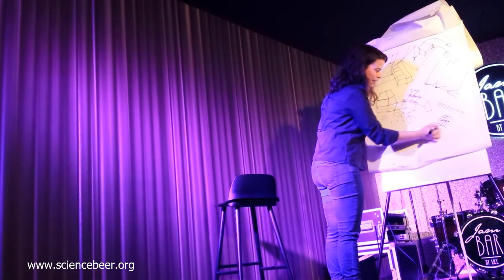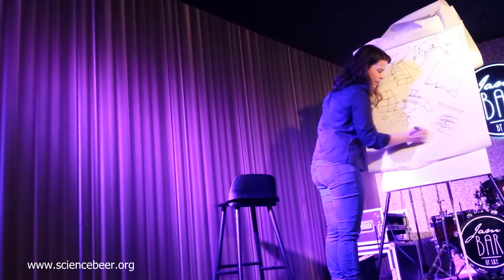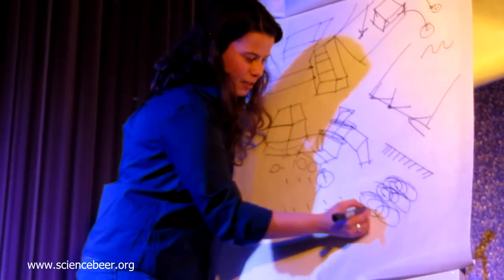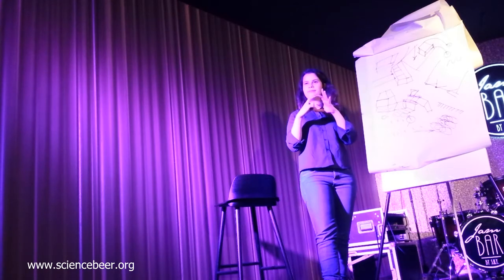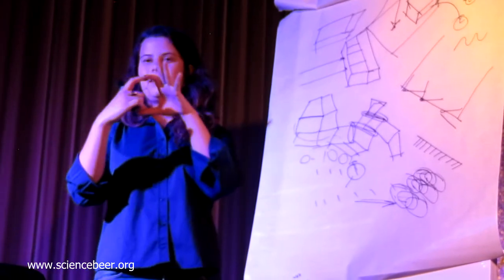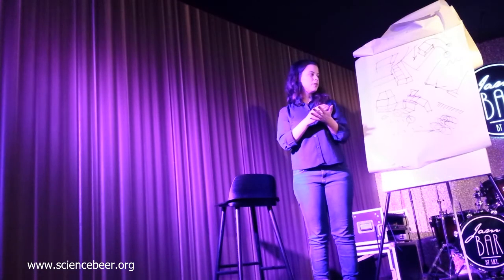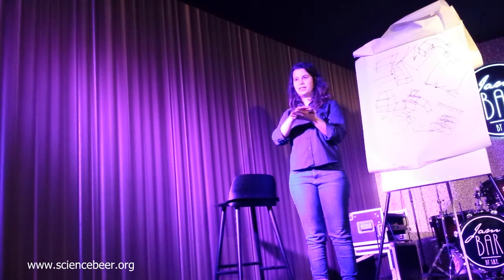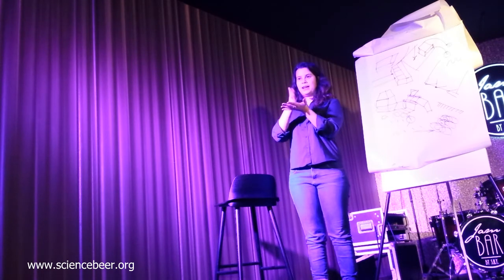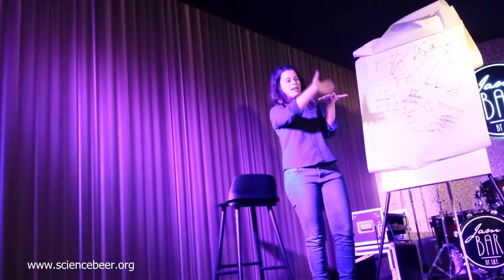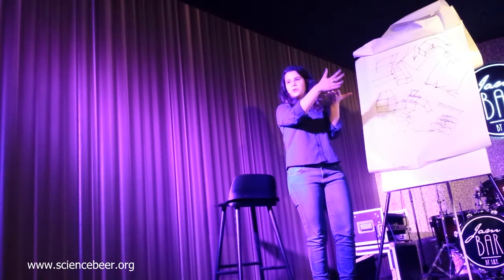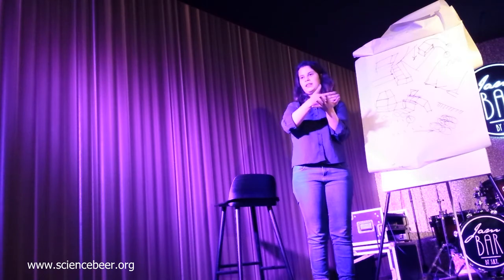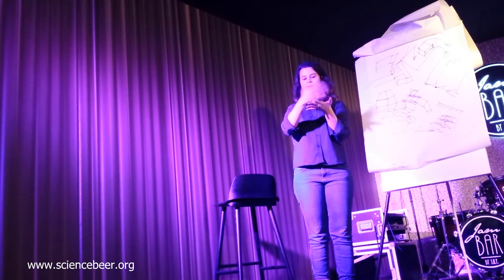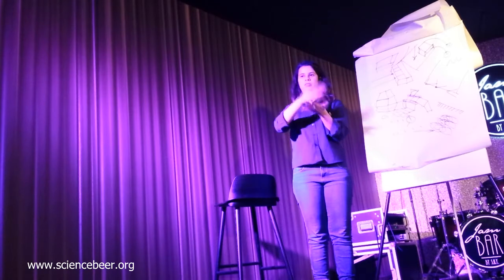We have the packing like this, and they have these pi-pi stackings, and the charge transfer happens from less strong bonds. They get delocalized and can flow through the packings of molecules. This treatment that we do is in order to guarantee wettability, that it adheres to our substrate, and that it packs in this way. So even with very edge-on structures this way, they would grow edge-on on the substrate in the other dimensions. So the problem is not really being edge-on. That is also for very thin films, they manage to have at least good control of this.